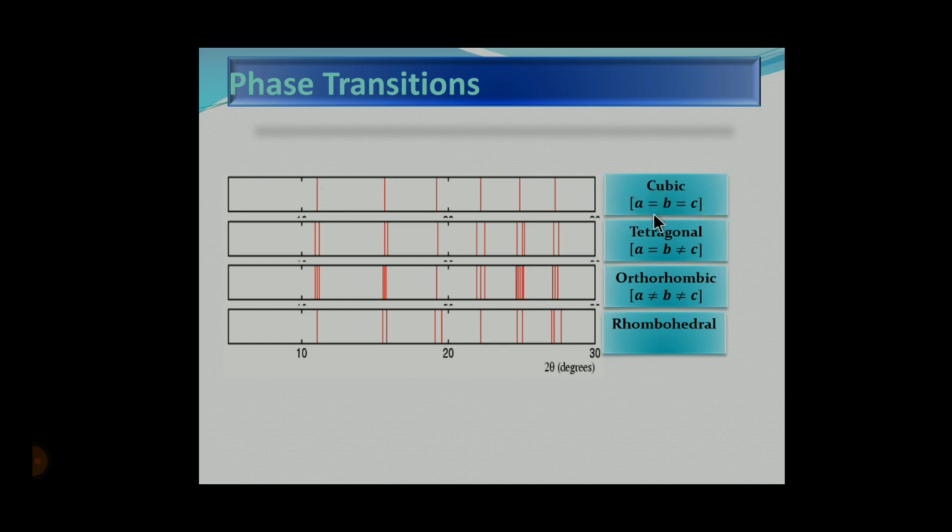But when it is heated up to some temperature, it changes into tetragonal structure. That is, the phase is being changed from cubic to tetragonal. And as you can see, for tetragonal structure, A equal to B, two dimensions are the same, but the third one is different. So there we got an extra line in the spectrum. So a single line for the cubic is being changed into a doublet. That is two lines. And again on heating, the tetragonal transforms to orthorhombic structure where all the